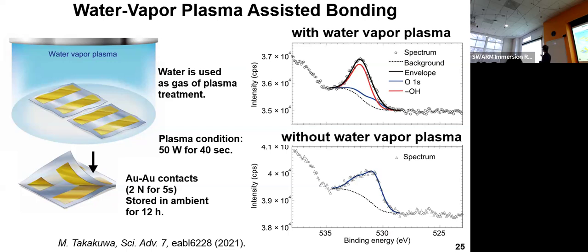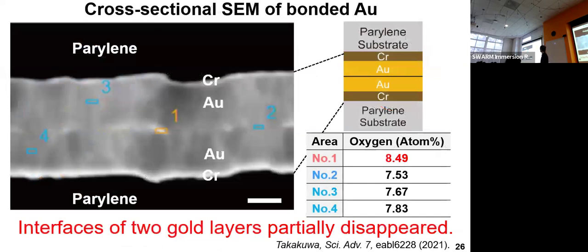And then here, the right side shows the XPS analysis of the gold surfaces before and after the water vapor plasma treatment. When we apply the water vapor plasma, OH group related signals are generated on the surface of the gold. So we expect that the OH group can help to make the bondings. And here is the proof of the direct, almost perfect bonding at the interface of the gold and the gold. We separately fabricated gold films, and then we did this bonding technology, and then we see almost perfect bonding. Here the interface has almost no color change, no contrast.